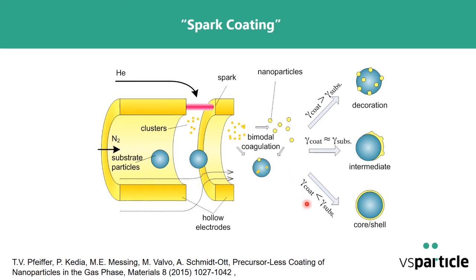In the case where the coating has a smaller surface free energy than the substrate, then you get a core shell particle. And more interesting for catalysts is when the coating has a higher surface free energy than the substrate. And this is what you typically have when the substrate is an oxide and the catalyst is a metal. Then you get something that we can call a decoration that you usually have for catalysts.